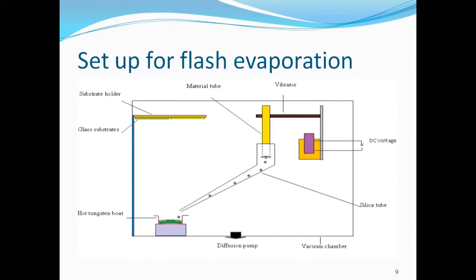You can see now I'm not able to see my cursor, sorry. Now you can see the label material tube. It is connected to the vibrator. It will dispense the powder so that we have the three components, selenium, bismuth, and tin. Whichever arrives on the hot tungsten boat is just evaporated instantly, and this is done in the vacuum.